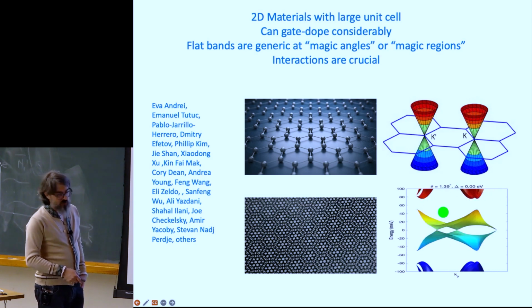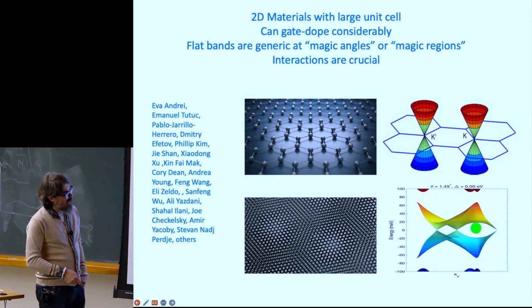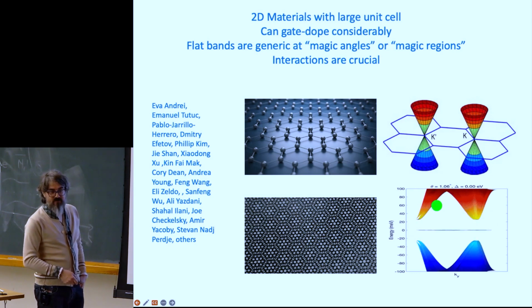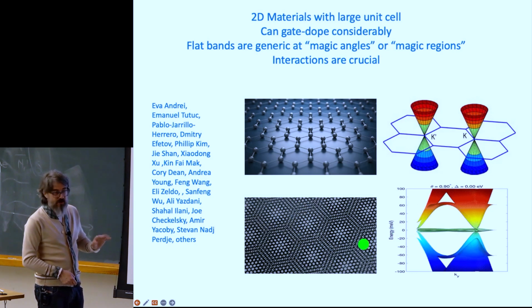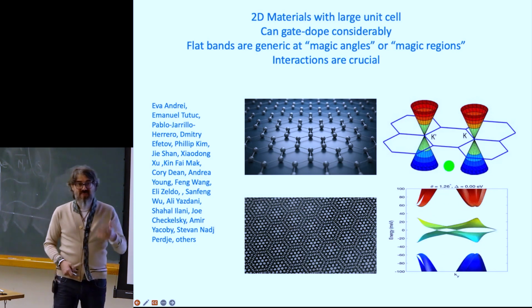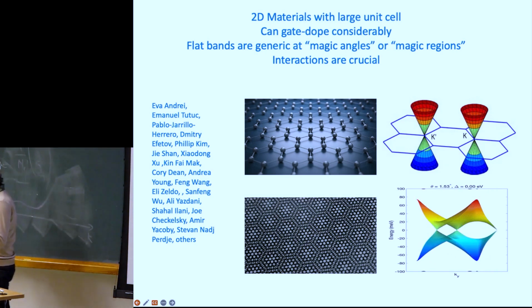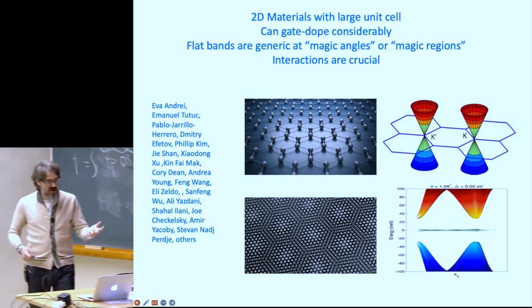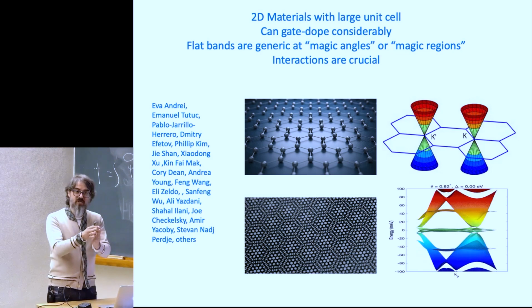But as you twist the angle to 1.05 degrees, which is called the magic angle, this bandwidth has now become less than 5 milli-electron volts. This is the non-interacting band structure. That's a 1,000-fold decrease in the bandwidth, from 6 electron volts to less than 5 milli-electron volts, by just twisting by a small angle.